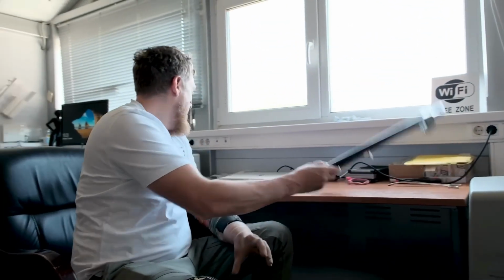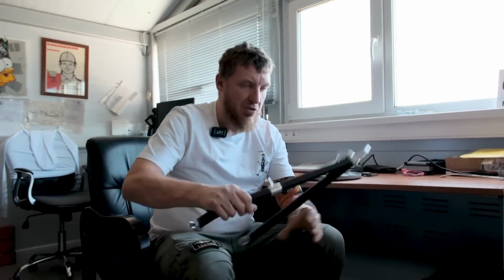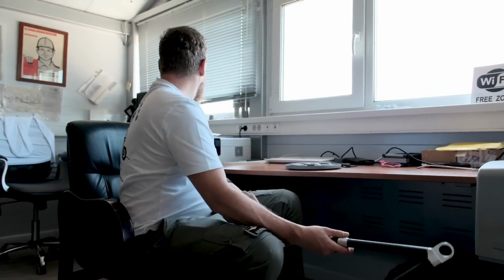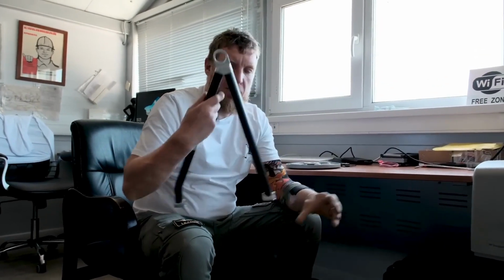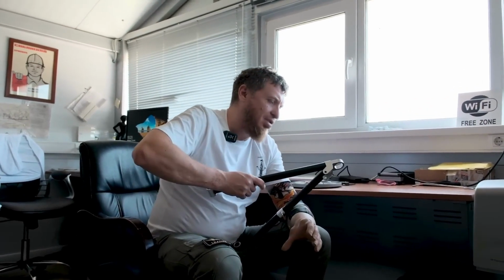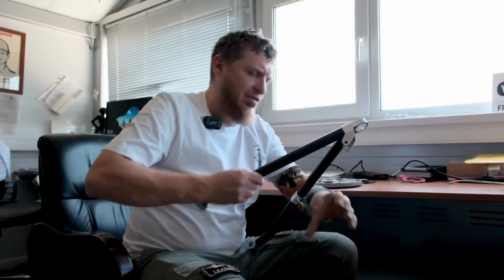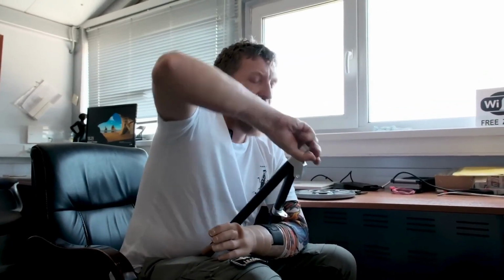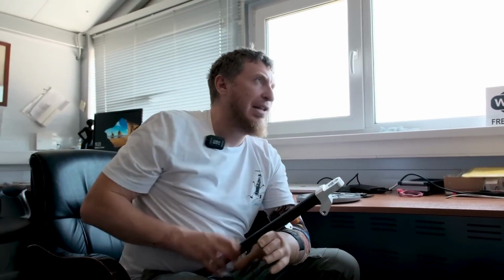And here is one of the levers. This is what the lever looks like after the process. I don't have the old one to compare side by side, but it's much lighter in weight. It's about half as light. We broke one on a tensile testing machine, 1.5 tons. It held up to about here, and then the aluminum eyelet broke.